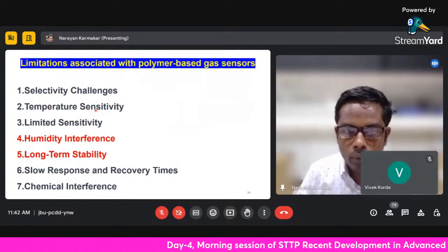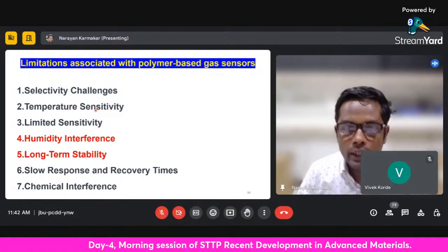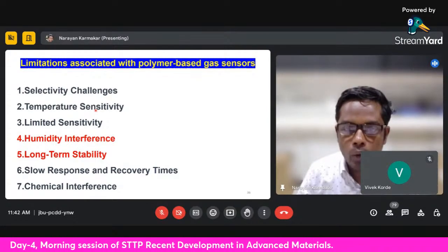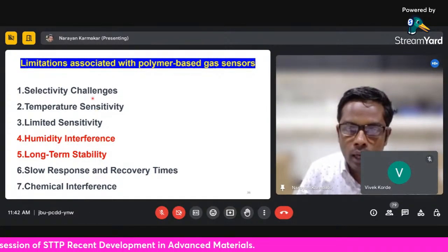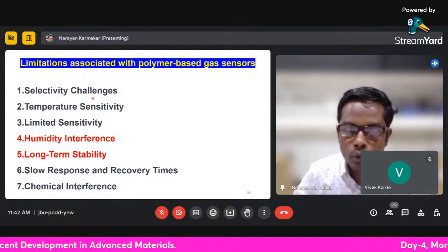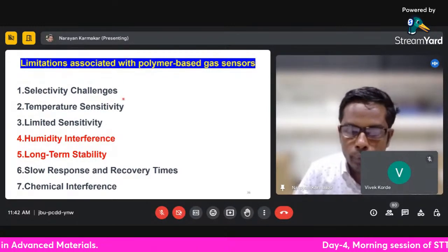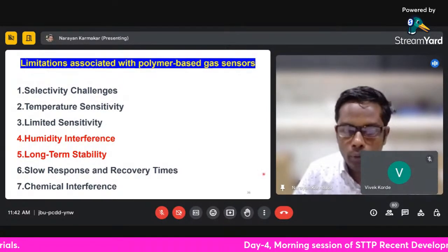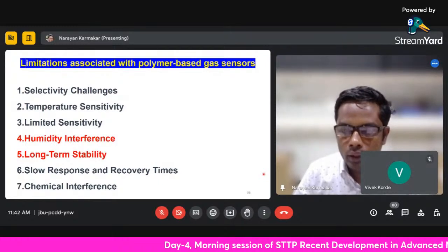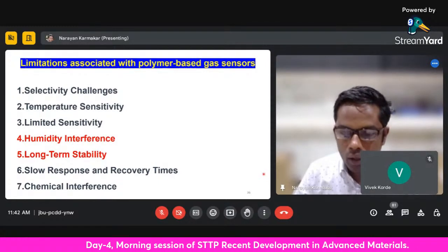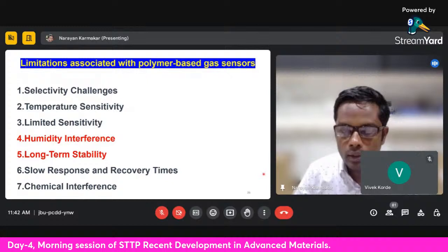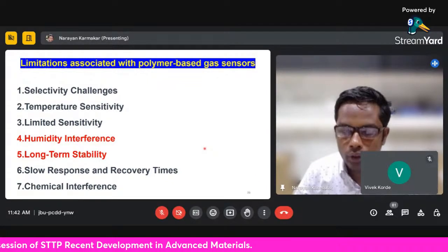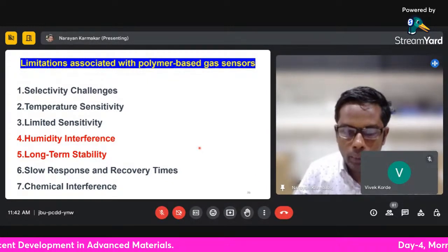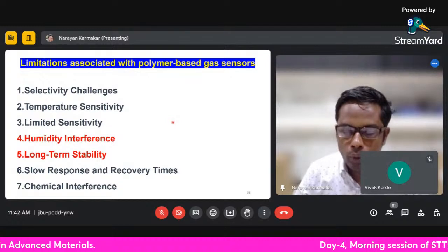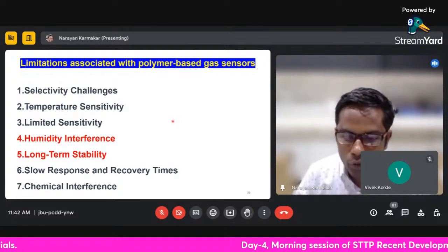Depending upon the metal or the metal oxide, which are sensitive to some specific gases, we make nanocomposites of these with the conducting polymer, and we synthesize this nanocomposite to operate the sensors at room temperature. The second problem with this is the temperature sensitivity. The sensitivity and the stability of polymer-based sensors can be influenced by temperature variation. So any changes in the operating temperature can affect the sensor performance, leading to inaccuracy in the gas concentration.